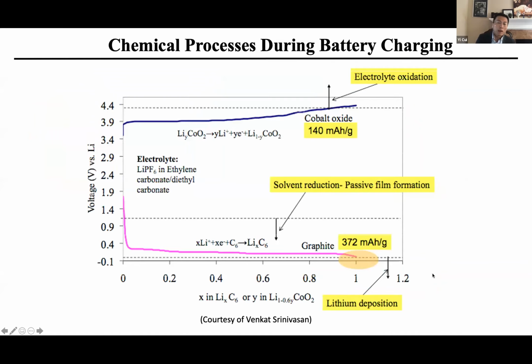So during lithium-ion battery operation, if you plot the potential, the voltage, with the cathode on top and the anode at the bottom, if you look at the anode during charging, lithium ions are coming in, electrons coming in, you have this plateau, and the graphite starts to take in a lot of lithium. Make sure you don't go below the graphite potential down to lithium plating. If it goes below 0 volt versus lithium metal, you can deposit lithium metal. I'm going to come back to that and how temperature will affect this process.